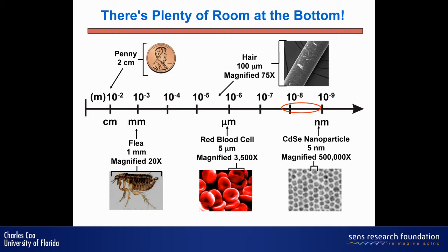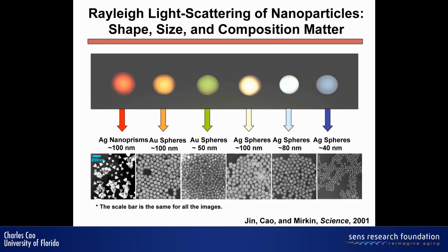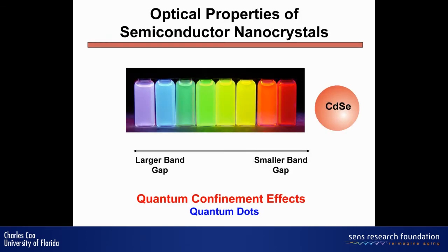If you shrink the size of materials, one thing is you can easily generate different colors. This is from size, shape, and composition of nanoparticles. Even more amazing: if you use one material and just shrink its size, you get different colors. This comes from a quantum confinement effect. When the size of particles is close to the diameter of the exciton radius, we observe emission from the particles — the emission changes significantly.